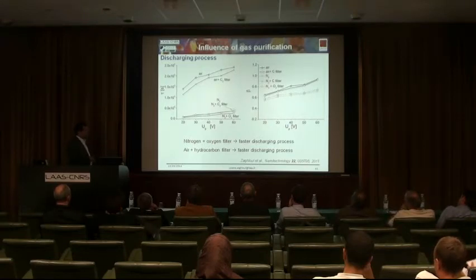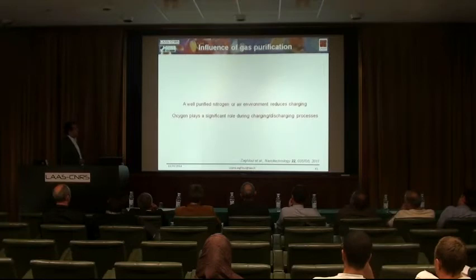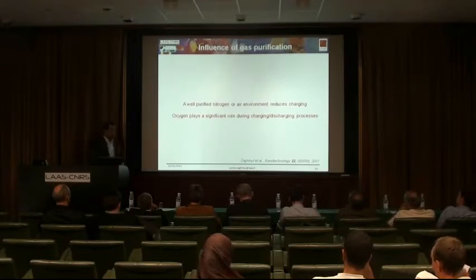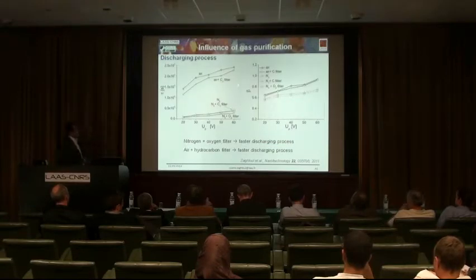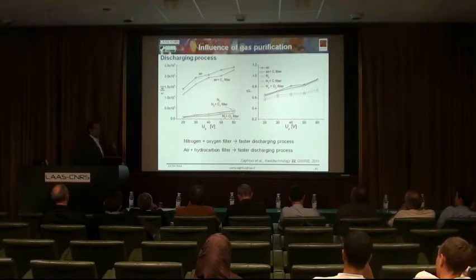Which means using a well-purified environment, free from hydrocarbons and organic contaminants, reduces the injected discharge density and speeds up the discharging process. You might say the difference is not really big, the difference is small. I just say be careful, this is the result of 1 second discharge injection.